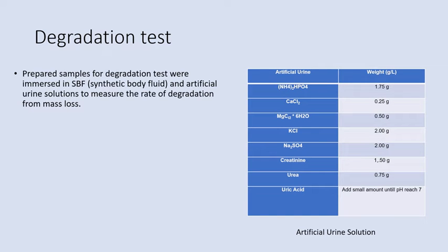Now this is the degradation test, and it is very important because we are putting this stent into our body, and we need a rate to say when it will completely dissolve. In order to determine this time, we run this degradation test. The samples we prepare for this test are 5 mm long and 3 mm in diameter. The prepared samples were immersed in synthetic body fluid and artificial urine solution. As I mentioned, we will put this into the body, and to create a body environment, we prepare this artificial urine solution. You can see the materials we use here, and we make this test to rate how it will dissolve in our body completely.